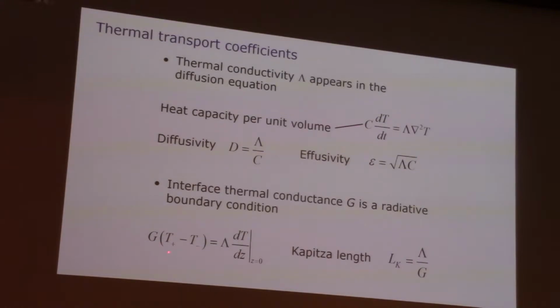This is the interface conductance. That's a radiative boundary condition on the temperature. This is basically the same equation I wrote on the previous slide. This is the heat current in the material. This is the temperature drop. That's the interface conductance. And sometimes we like to think about this term as the ratio of these. So I take thermal conductivity divided by thermal conductance of the interface. That has units of a length.